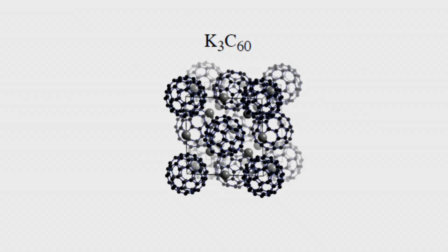However, there is another one, let us show that. This is called K3C60. These huge buckyball structures, or fullerenes, are occupying the body-centered positions of a cube, and this has a larger Tc. Tc is about 18 Kelvin. And by using various organic compounds, the Tc could go all the way up to 30 to 35 Kelvin. That is the maximum Tc that one could achieve with organic superconductors.